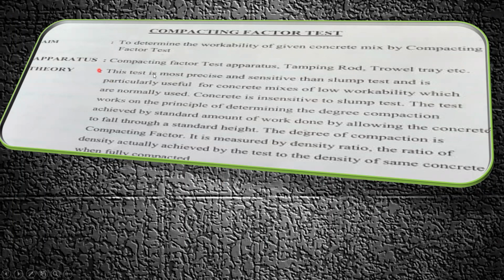Coming to the theory, this test is more precise and sensitive than the slump test and is particularly useful for concrete mixes of low workability, which are normally used. Such concrete is insensitive to the slump test. The test works on the principle of determining the degree of compaction achieved by a standard amount of work done, by allowing the concrete to fall through a standard height.